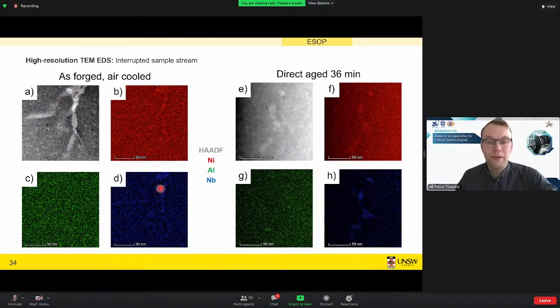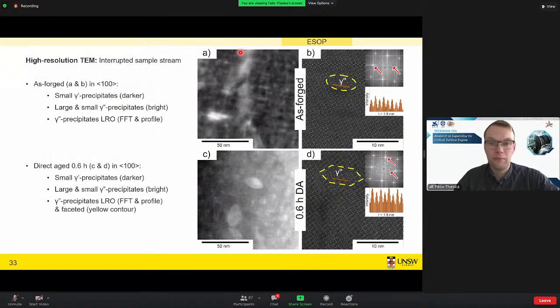Yes. So maybe I start with the sample preparation, because that was one of our concerns too. All the atom probe samples and all TEM samples have been electropolished. You grind a very thin foil, make it a disc, and then electropolish it. So you have no contamination from the FIB and no deformation left over from any grinding steps. The challenge is getting samples suitable for this high resolution TEM. It took me a bunch of attempts to get a very, very thin sample. So you need a couple of attempts to get good enough samples.